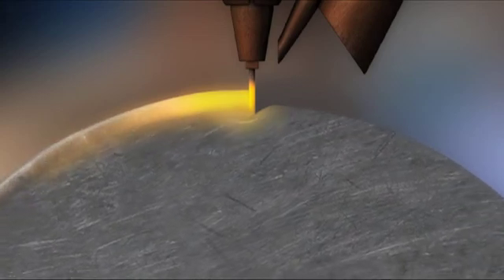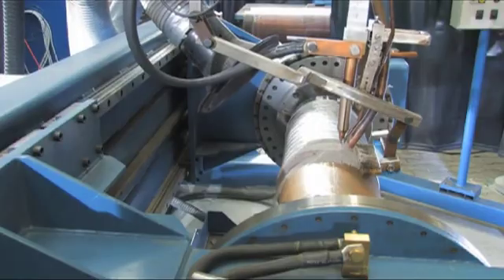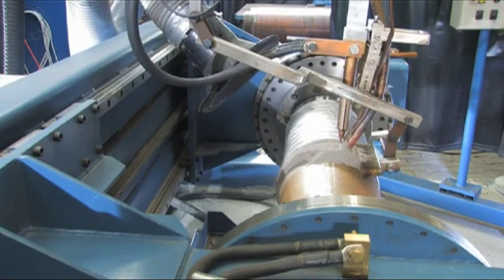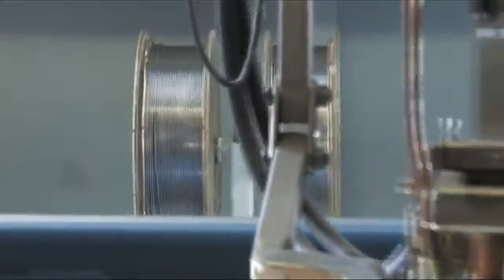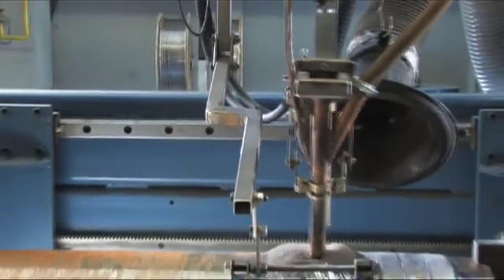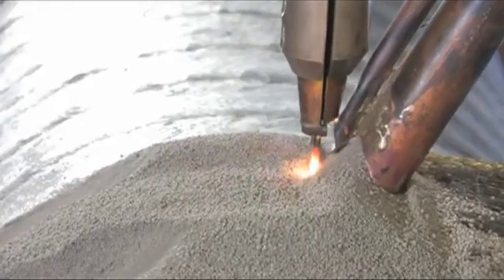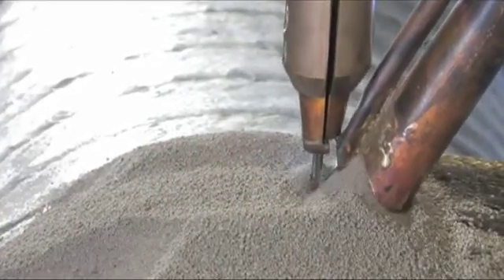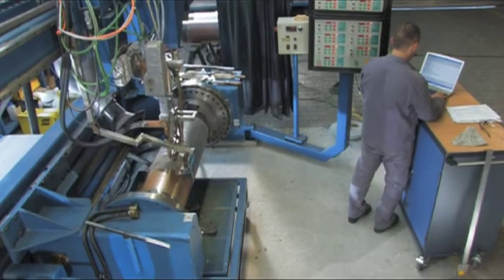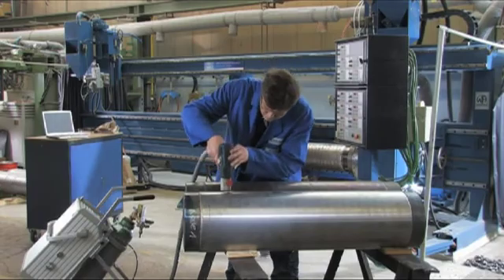The advantage of HPS: the wear-resistant coating is produced from the welding material and the molten basic material of the roll. The single layer technology combines high-alloyed welding wires by adding metal powder so that a completely homogeneous coating is produced. Using cord wire and metal powder, the chemical analysis and the hardness of the layer can be adjusted according to requirements.